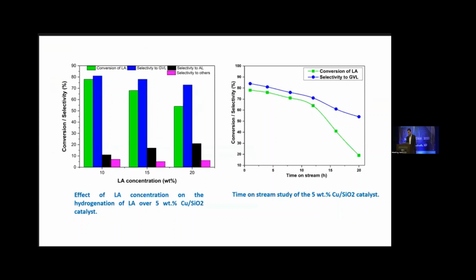So we also explore the levulinic acid concentration, and 10 weight percent is showing the highest conversion and selectivity. And for stability, mesoporous silica is showing better performance than hydroxyapatite due to the higher surface area of mesoporous silica, which reaches 1,000 meters squared per gram.